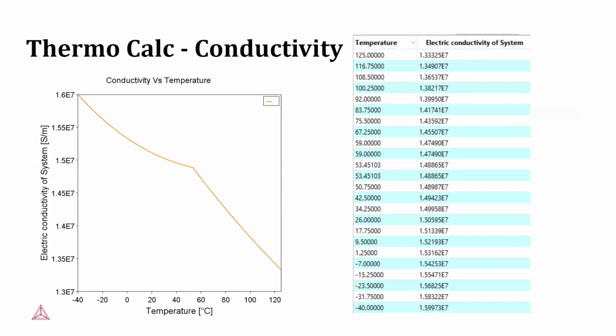And so we see here, ThermoCalc shows us how the conductivity changes as the temperature increases or decreases. At around 50-something degrees, there's a shift, and that is likely due to the BCC phase forming. ThermoCalc shows it as if it happened perfectly instantaneously. In an actual material, you'd expect that to change more gradually because diffusion does not happen right away.